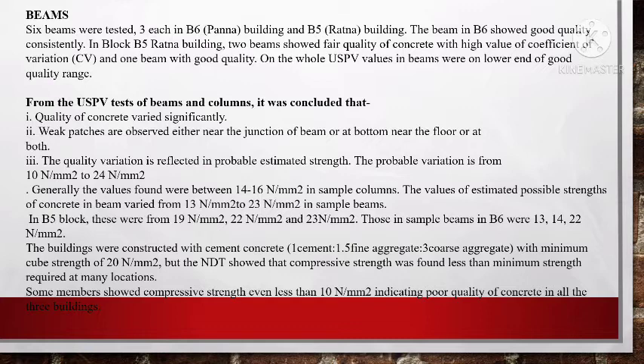From the USPV tests of beams and columns, it was concluded that quality of concrete varied significantly. Weak patches are observed either near the junction of beam, or at the bottom near the floors, or at both. The quality variation is reflected in probable estimated strength. The probable variation is from 10 Newton per mm square to 24 Newton per mm square. Generally, the values were found between 14 to 16 Newton per mm square in sample columns.